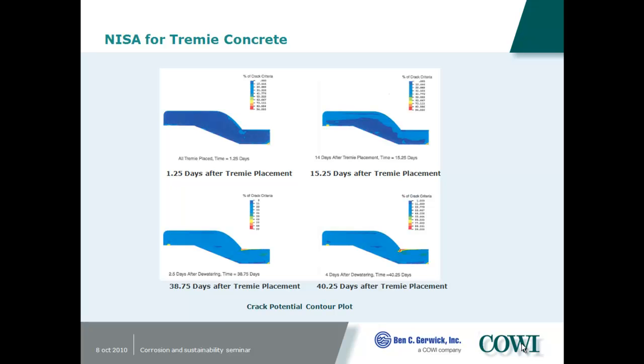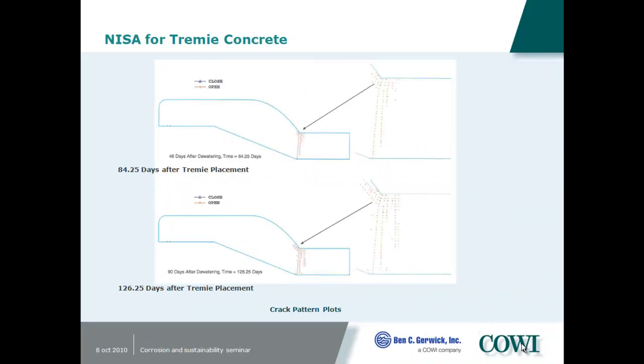And as you would expect, the crack potential is highest right where there's a reentrant corner, a stress concentration, and this just shows that it's at 99% of the crack criteria, so that's just under the crack criteria there. But even if it does crack, most people assume concrete is cracked. That's why there's reinforcing across it.